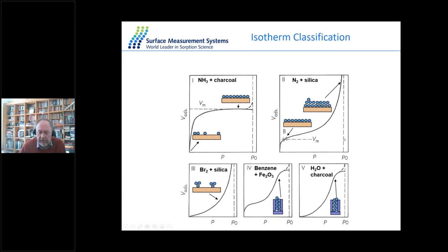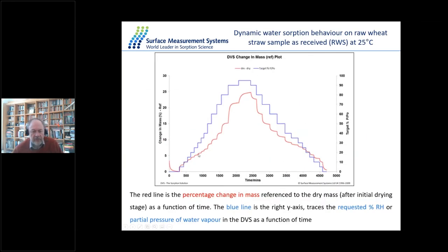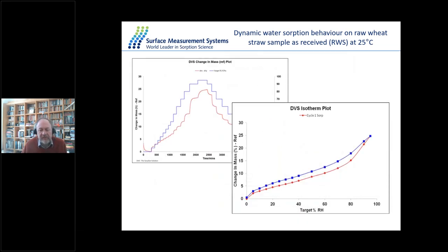For some of the materials that we're looking at here, you can notice how slow the kinetics are. This experiment took a few days. So what this tells us, because there are slow kinetics, is this is not water molecules on the surface of the straw particles or fibers. These slow kinetics mean the water molecules are dissolving into the molecular structure, into the polymeric or biopolymer fibers here. So this is around diffusion into some semicrystalline structures, which is why we get these slow kinetics. So the kinetics in their slow nature tells us this is a dissolution process, not a surface adsorption process.